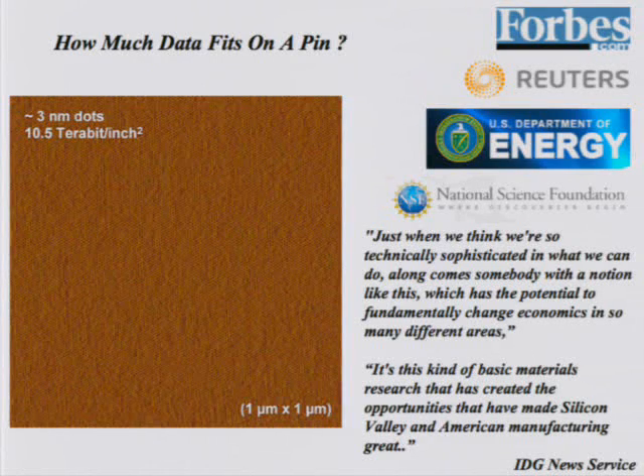By reducing the molecular weight, you can generate features as small as 3 nanometers, and that translates to 10.5 terabit per square inch. If you look at this versus Moore's law, we are about 1 to 2 orders of magnitude higher than the current state of the art.